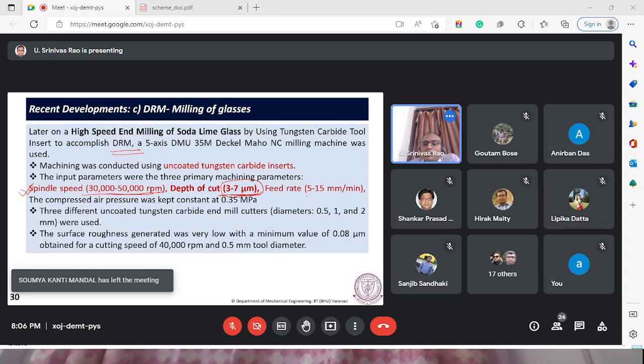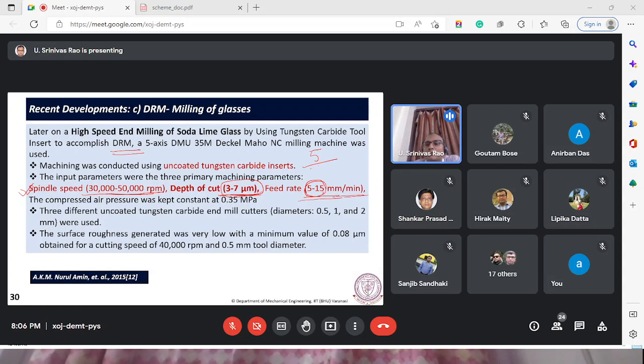And then the feed rate is 5 to 15 mm per minute. This looks like a big value, but if you take 5 divided by 30,000, that will be the feed per revolution. It is almost of the order of 10 to the power minus 4, which is a small value, almost 0.1 micrometer. These values give an idea about the challenge. That means we have to deal with a very small depth of cut and very small feed, so that actually motivates us to increase it.